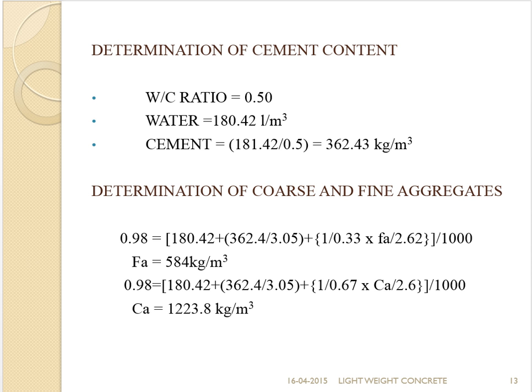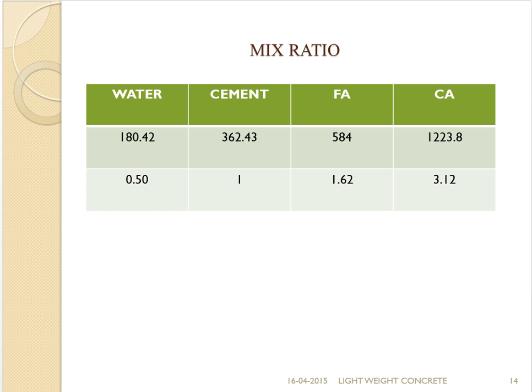The quantity of water we have used is 180.42 liter per meter cube, and the cement is 362.43 kg per meter cube. The fine aggregate is 584 kg per meter cube and coarse aggregate is 1223.8 kg per meter cube. This is the mix ratio, 1 is to 1.62 is to 3.12.